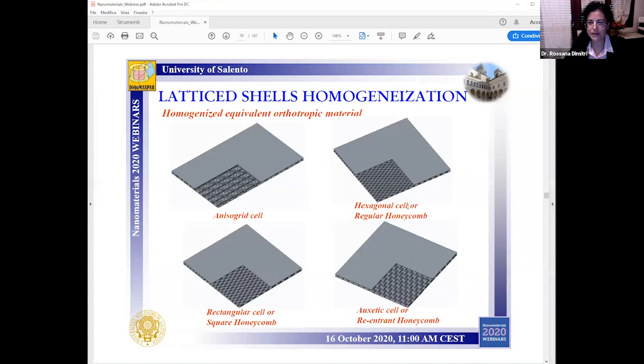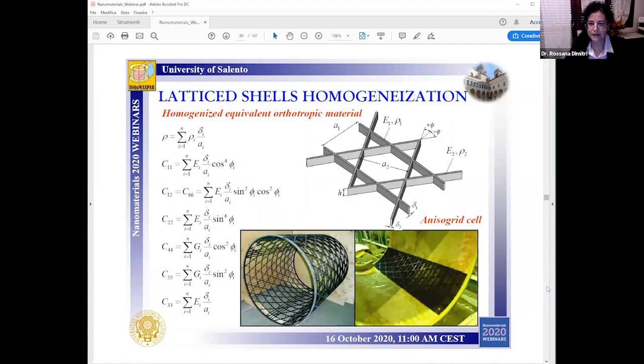So see here some examples of lattice structure with an anisogrid cell or a hexagonal cell, a rectangular cell, or an auxetic cell. So for a lattice layer, a first approximation could be to consider the equivalent orthotropic material whose equivalent constants for a unit cell could be computed as a function of the main geometrical and mechanical properties of the ribs.